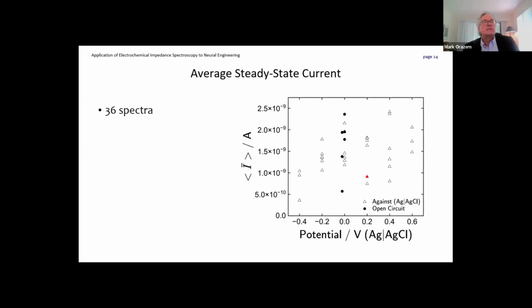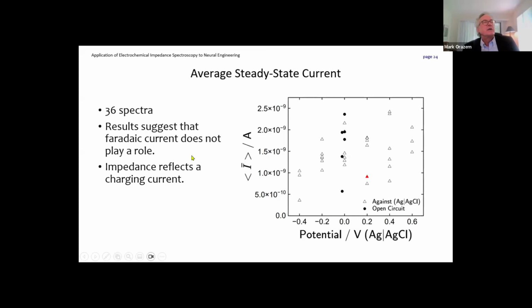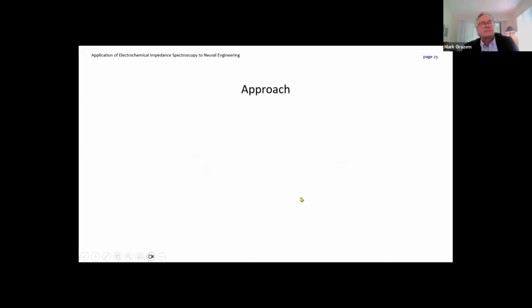And what this is telling us is that we've waited long enough, 15 seconds between measurements, to allow that to stabilize. There are 36 spectra. The results suggest that the Faradaic current is not playing a role, and the impedance then suggests that we're seeing really a charging current, not a Faradaic current.